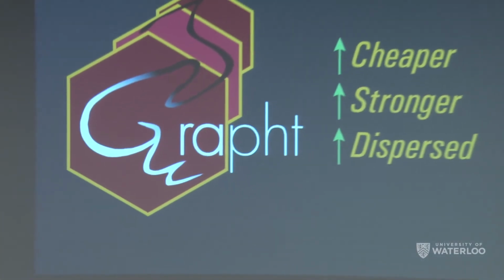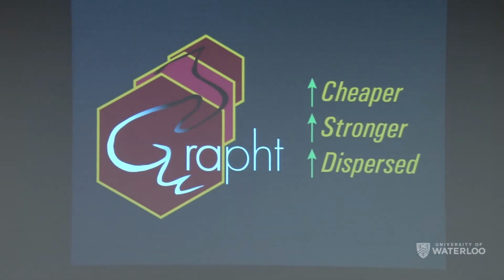So one interesting thing about the CNTs, the Grapht that we were able to make was because we used such high aspect ratio CNTs, the material that we made is actually really flexible, which is unusual for graphene added polymer mixes. So in short, Grapht is cheaper, stronger, it's well dispersed. You can use Grapht to put graphene into nearly anything you want to think of because of the flexible reaction mechanism and because of graphene's really, really good material properties.